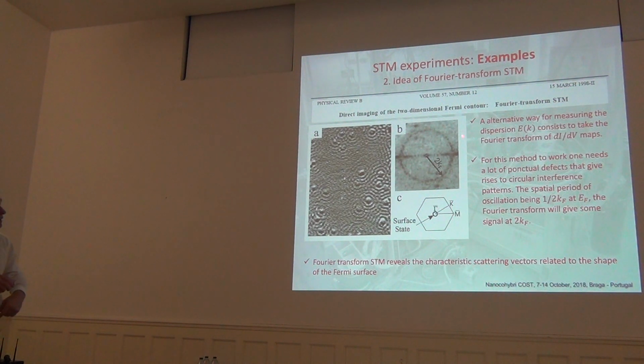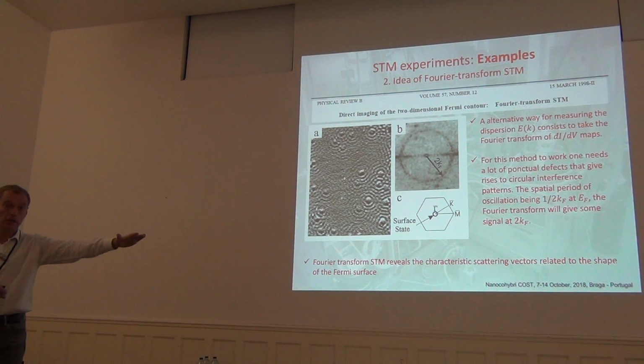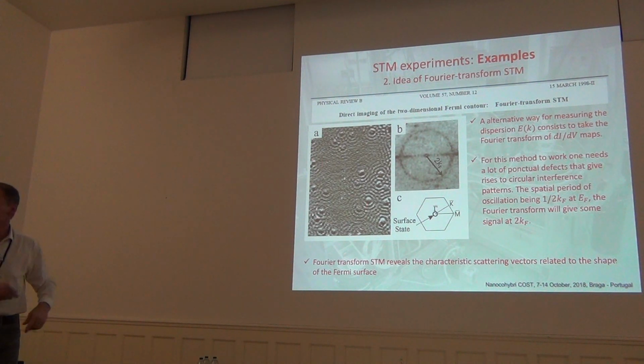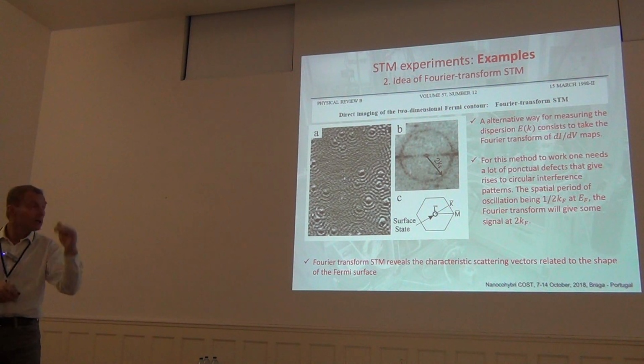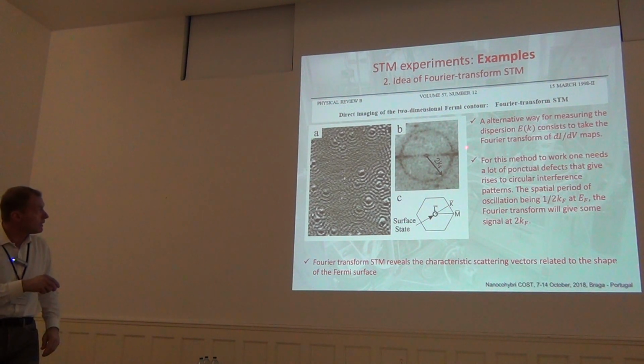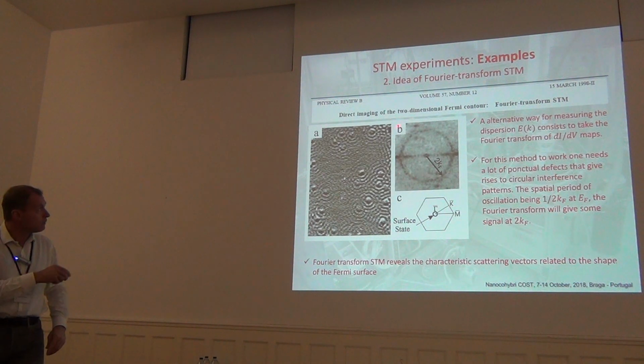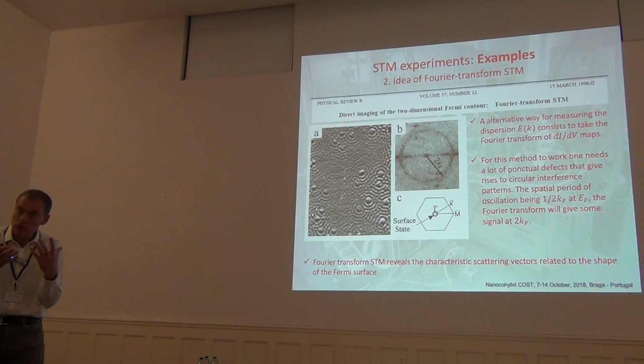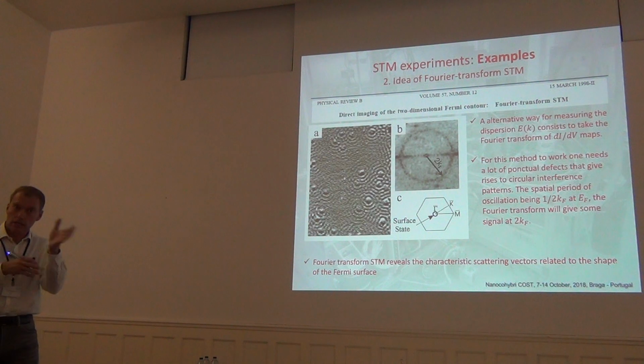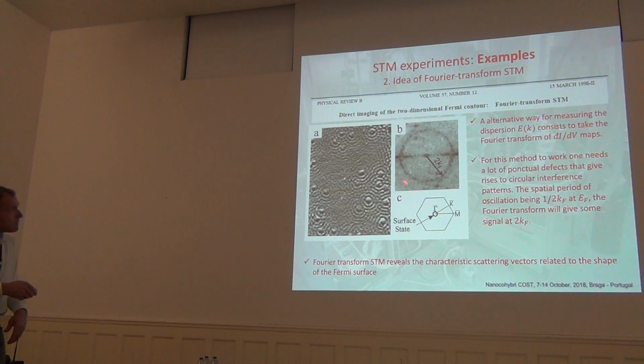And all these, they sit in the equi-energetic level that provided this image. If I do it for the Fermi energy, I will do k-space imaging of my scatterings, which are related to the Fermi surface. Okay? So I can map somehow the Fermi surface, and this is just 2 times k Fermi.